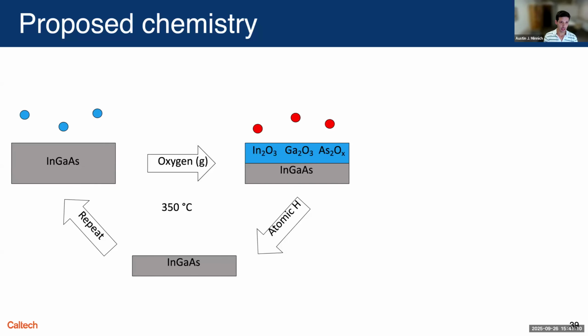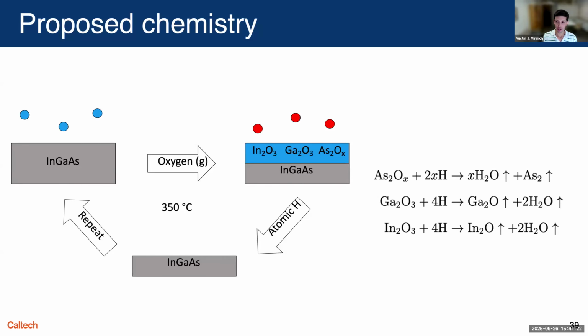All right, so this is the summary of the process. We take oxygen gas, we then use atomic hydrogen. This all is occurring at a pretty high temperature, although we've gotten it down recently. And the chemistry that's happening is probably the formation of suboxides, like gallium-2O or indium-2O, and they're pretty volatile. So when you reduce the initial oxides to those suboxides, you remove those elements.